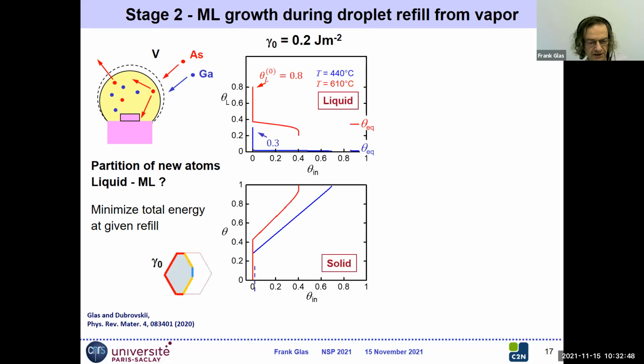So again, this quasi-static approach. So I don't give you the details of the calculations, but I show you the results. So the panels here are for relatively large edge energy of the monolayer. So at the bottom, we look at the coverage, so what happens in the solid, at a low temperature in blue, at a higher temperature in red.